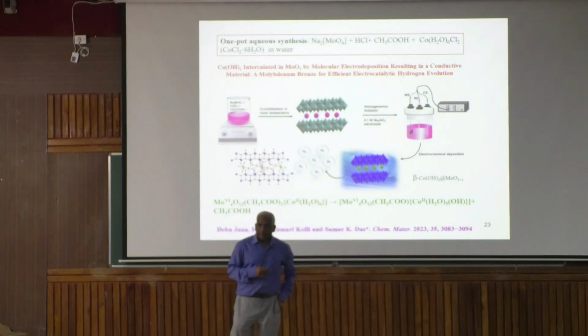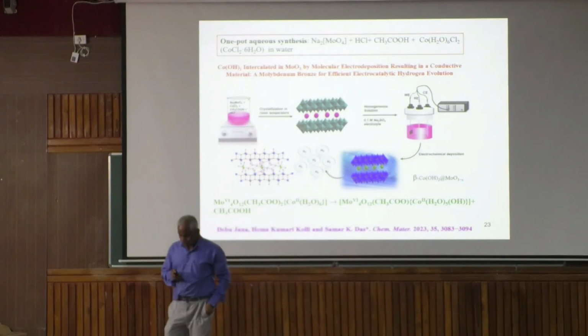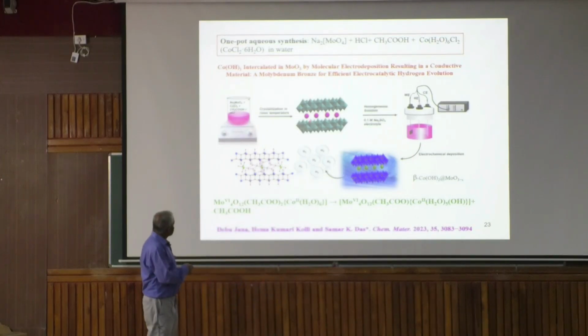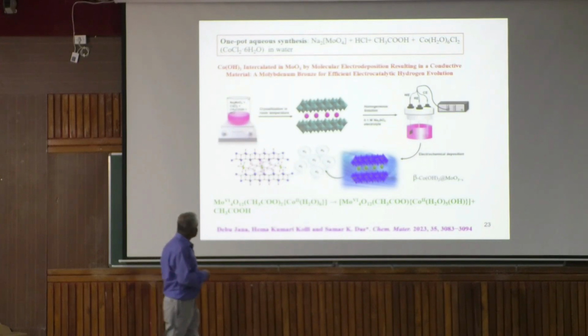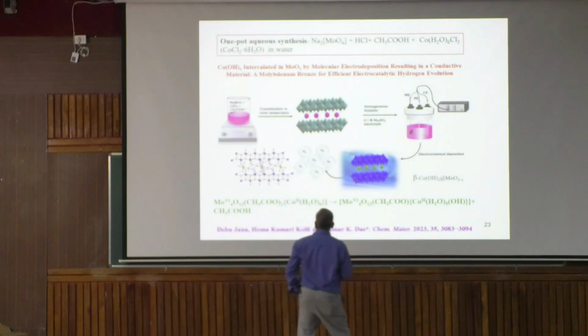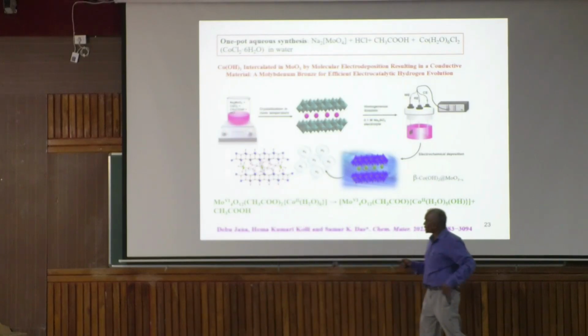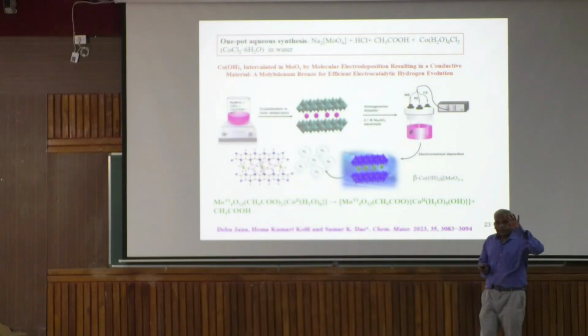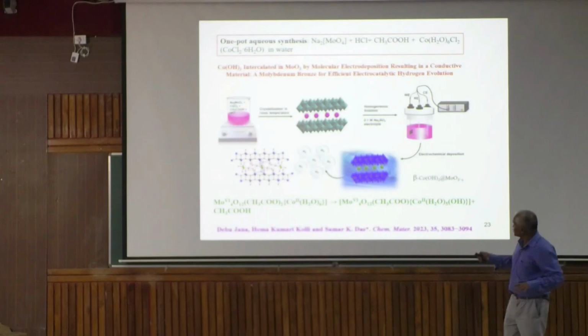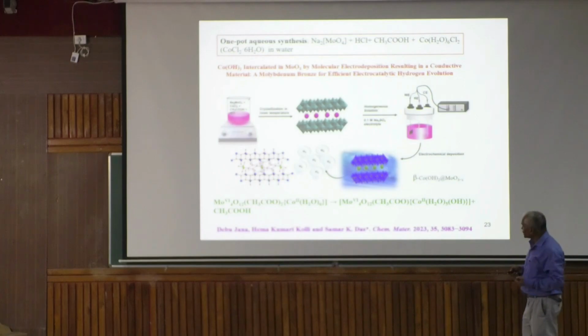Once we got nickel, what about cobalt? So cobalt also we did that. Same structure we got. We thought the same thing was happening, like cobalt. In this case also pH comes down, that this is an inorganic acid. But then with the electrode deposited material, we get hydrogen evolution, plenty, continuous hydrogen, it is a better catalyst than the earlier one.